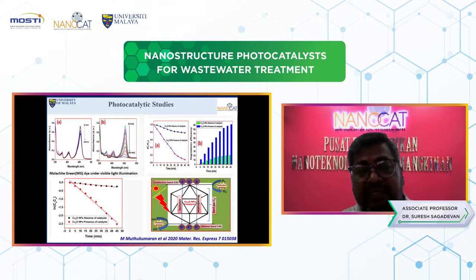So we did this work for malachite green under visible light illumination. There are two UV spectra, A and B. Figure A is in the absence of photocatalyst, and you can see that there is no change. But in the presence of photocatalyst, B, you can see significant changes. And as well, look at the Ct by C0 graph, how the dye is degraded in the presence of the catalyst.